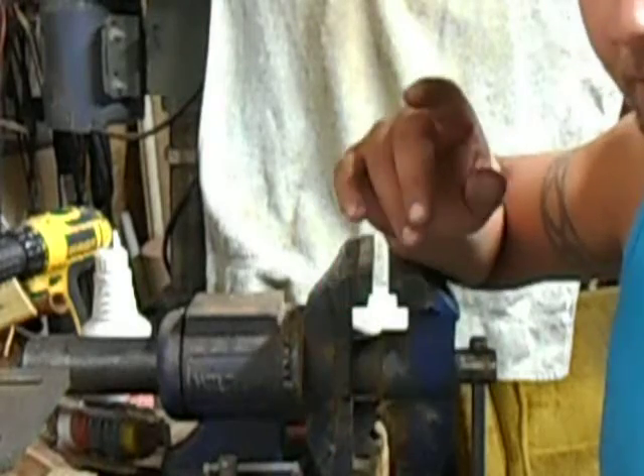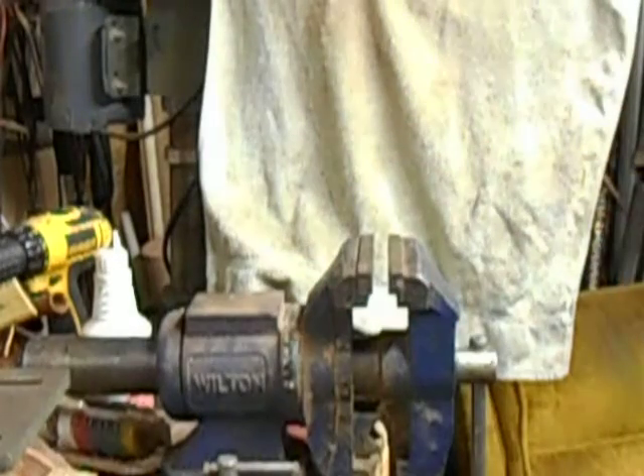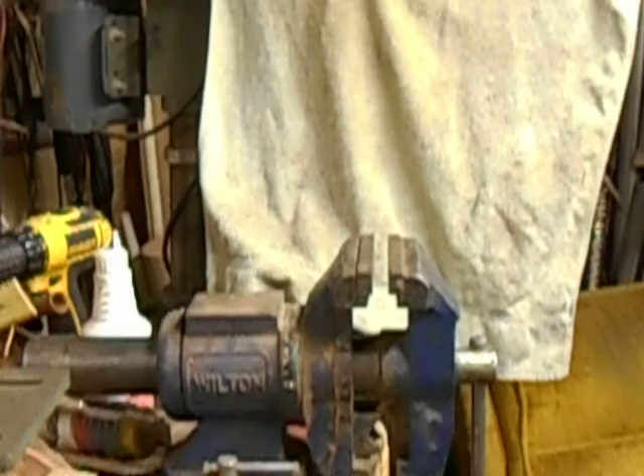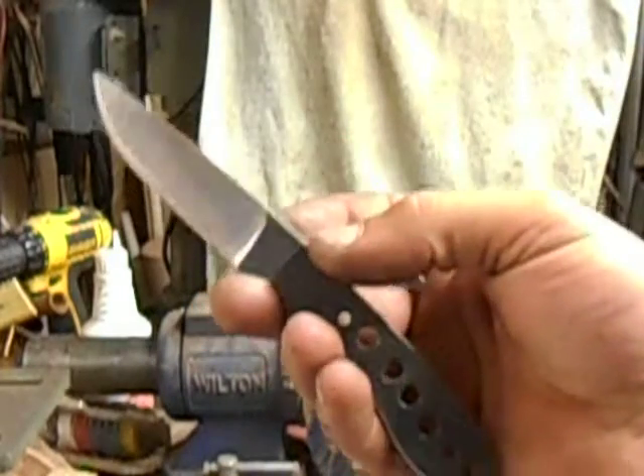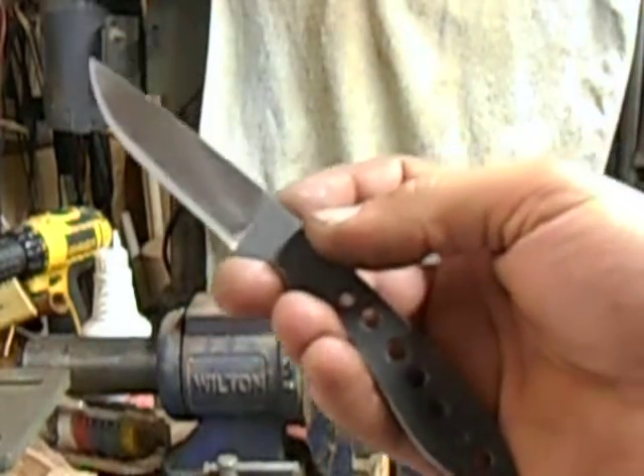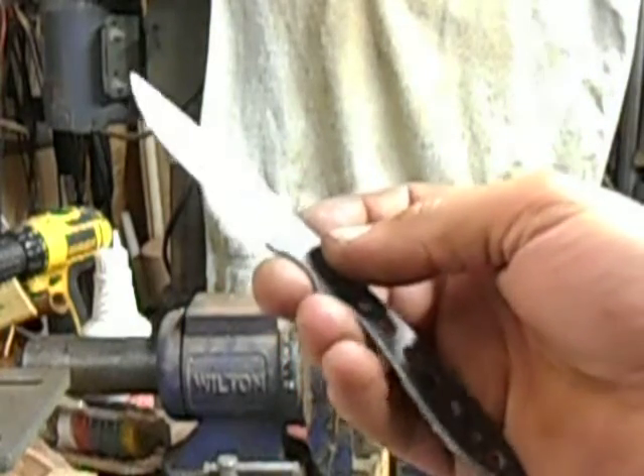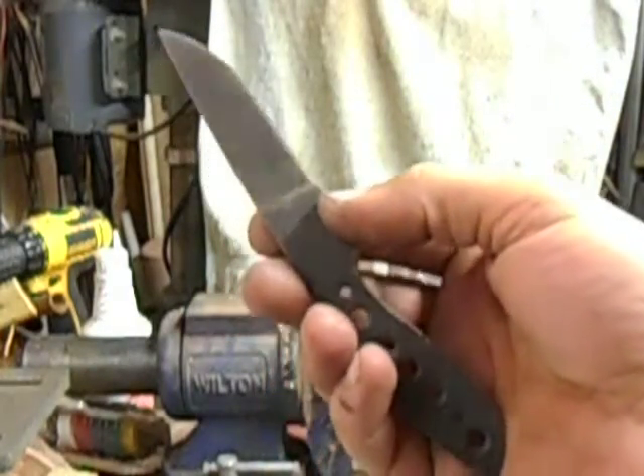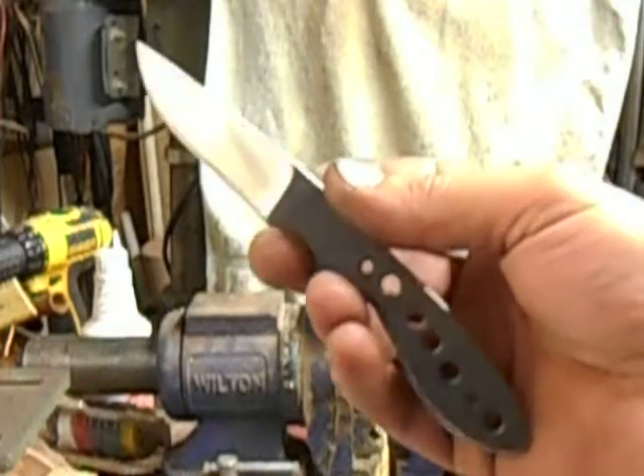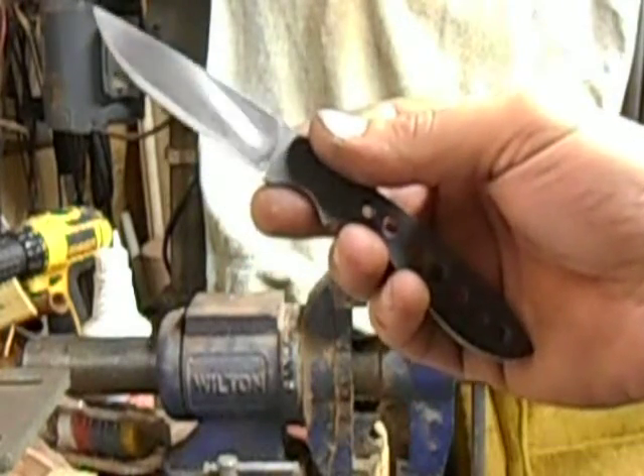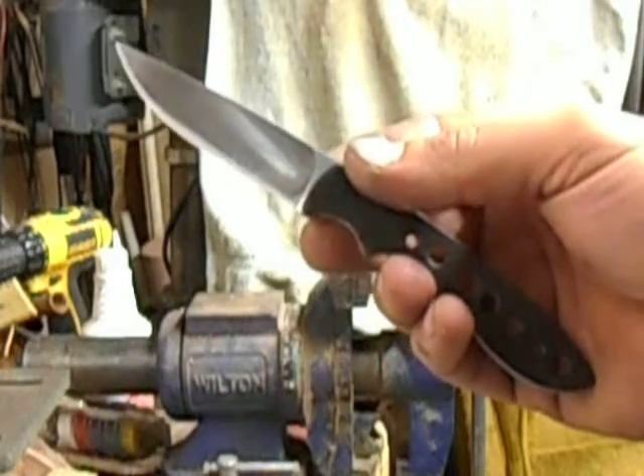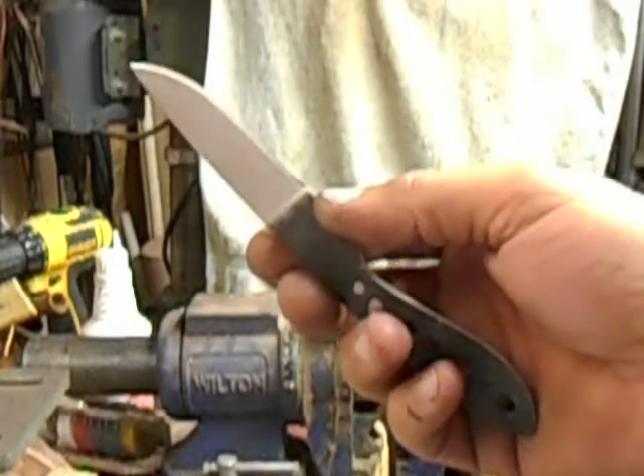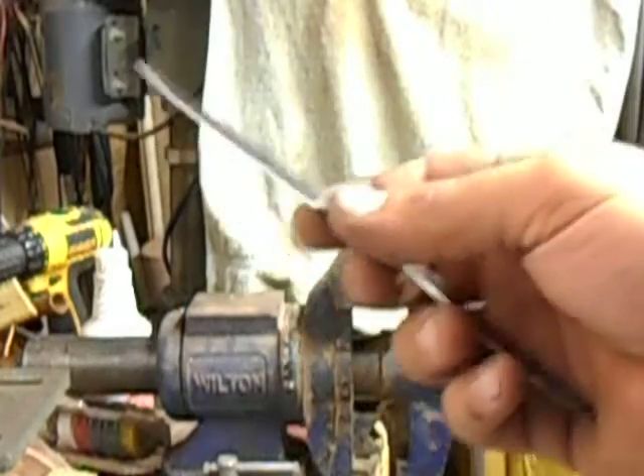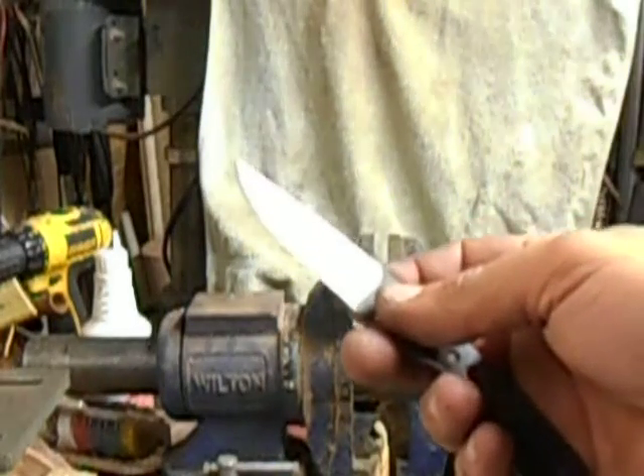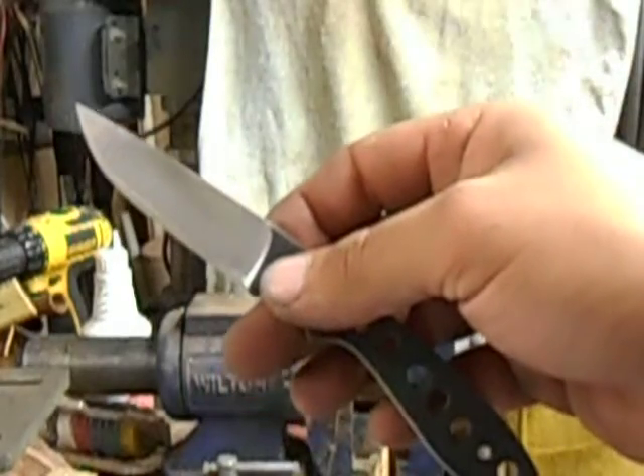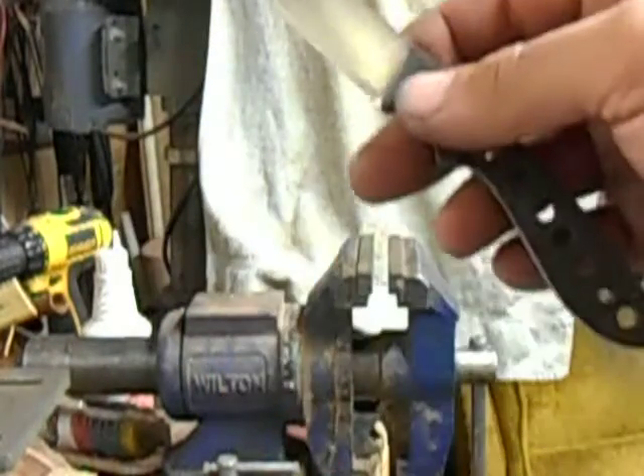I think I've got the actual tester that did the best in the cutting tests. This one right here. Again, this is Admiral's 440C stainless, 16th inch stock, straight as they shipped it to me, which they said is fully annealed. Bring the kiln up to 1900 degrees Fahrenheit. Place the blade in the kiln. 15 minutes later, pull it out.